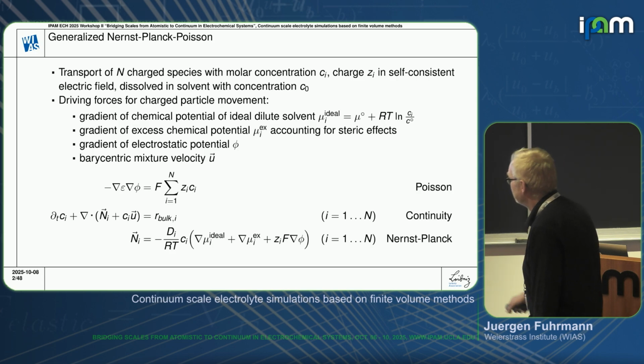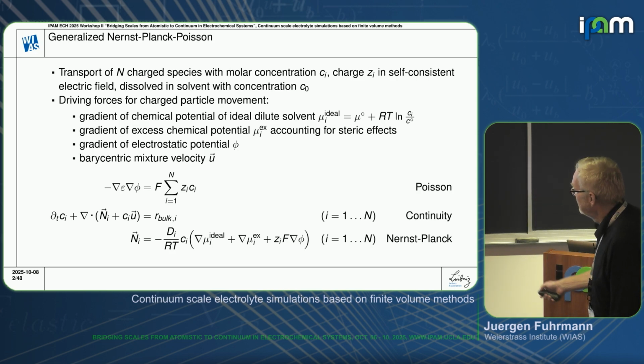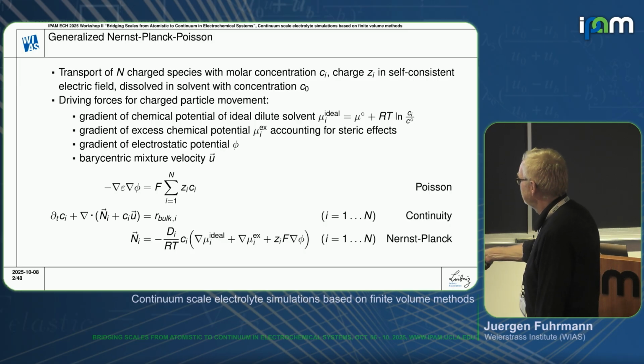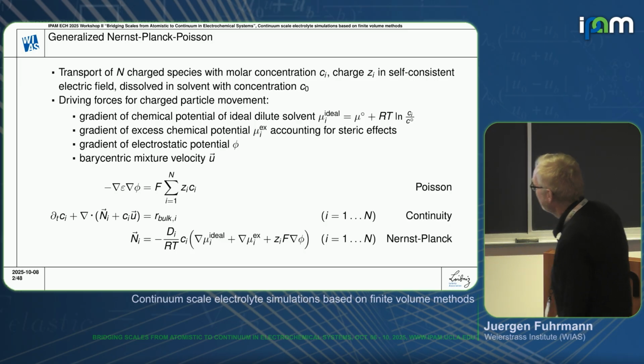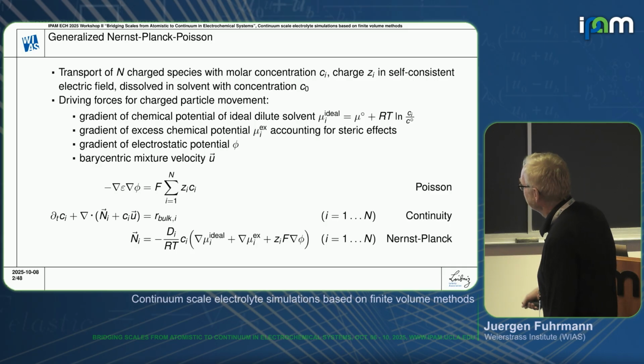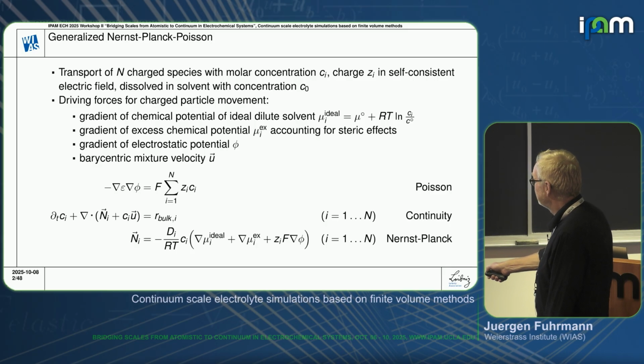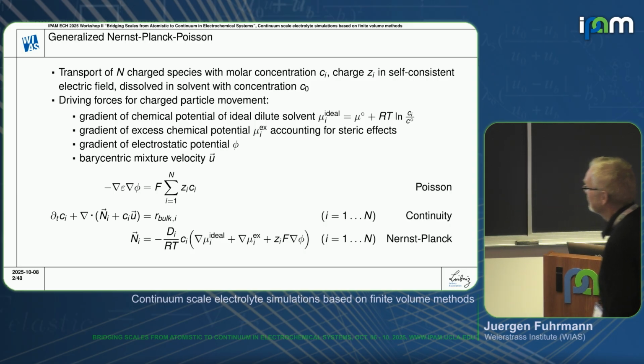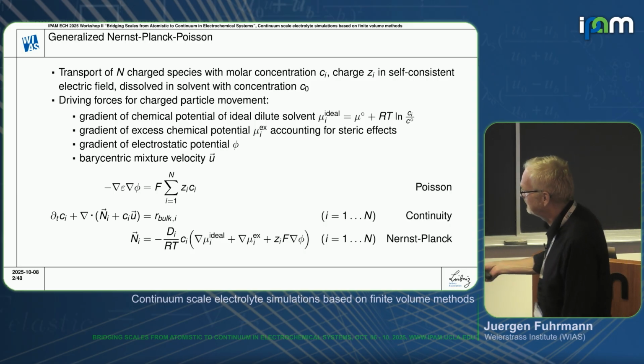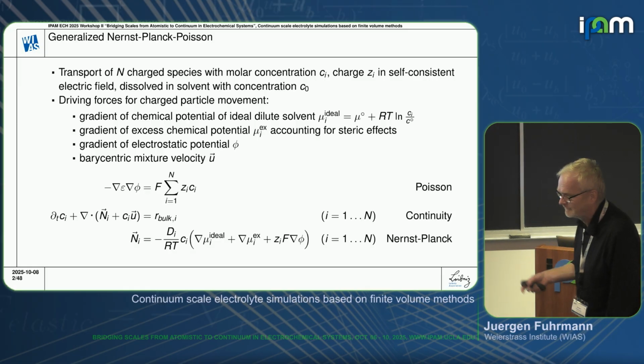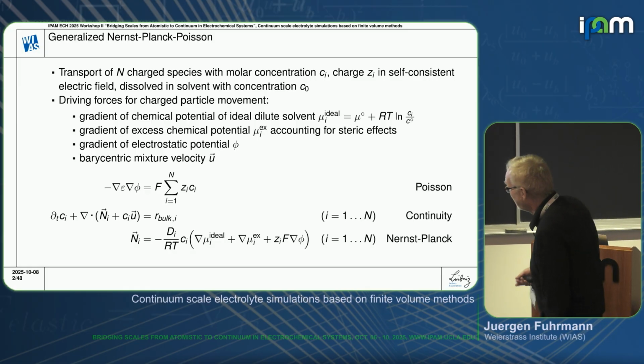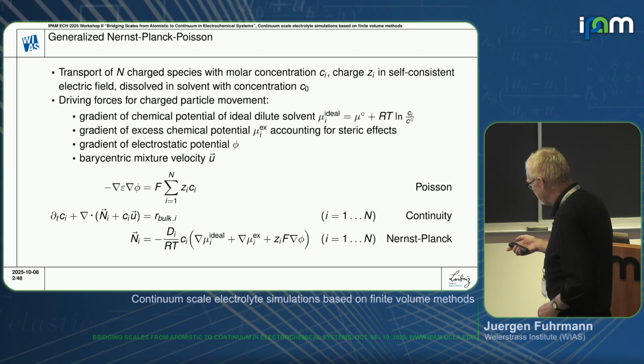We have the gradient of the electrostatic potential, multiplied by the charge number, and here I'm writing this in molar quantities, so we have the Faraday constant instead of the electron charge. And we have another term, the gradient of the so-called excess chemical potential, which can take into account all kinds of non-ideal interactions, in particular steric interactions.